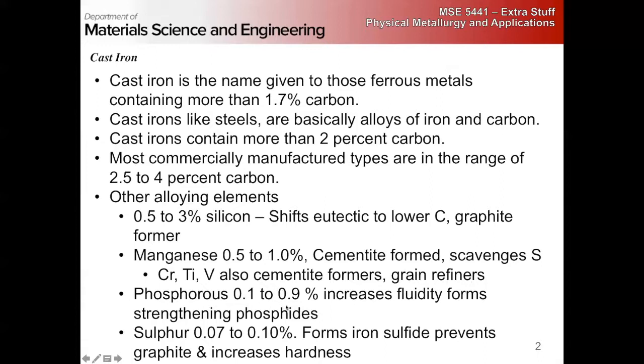Phosphorus is important for casting — it reduces the viscosity and increases the fluidity, and it also forms strengthening phosphides. Sulfur can either be an impurity if it's greater than 0.1%, or a beneficial alloying element in smaller ranges. It forms iron sulfide which prevents graphite, but the sulfides also increase hardness and strength.